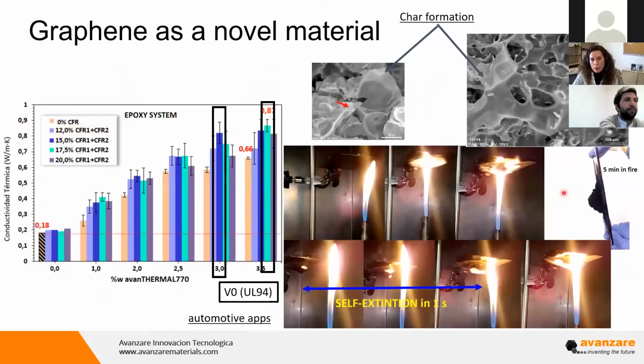Apart from electrical and thermal conductivity, as you surely know, these materials also have an effect on mechanical properties or other applications, as for example, flame retardancy. Here, what we are observing is different weight percentages of graphene material in combination with other flame retardant materials. So we can obtain about 1 Siemens per meter, near to 1 watt per meter Kelvin, and V0 according to the UL 94 fire regulation. So with this formulation, we are preparing materials, for example, for automotive applications, or, as we will see later, the building sector, which has a good fire classification, with self-extinction after a long time, because thanks to graphene, we are improving the fire performance through the char formation on the surfaces.